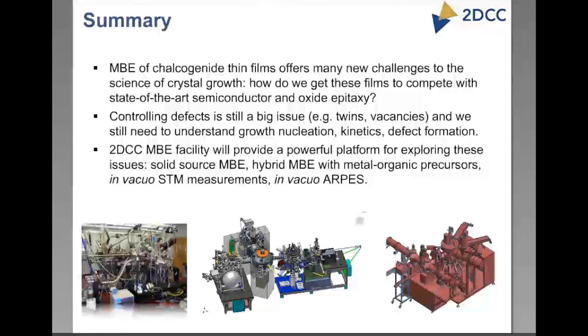Again, to give you some sense, with my current MBE chambers, which are an EPI 620 and an EPI 930, I mean the 3.5 chamber, we don't really open it up that often, maybe twice a year. And the bismuth chalcogenide chamber, we open it up and we are back in business within 10 days. So I'm guessing this is a smallish chamber, and if we do have to vent, getting back to business is not going to take that long.